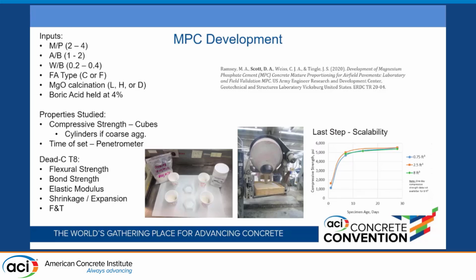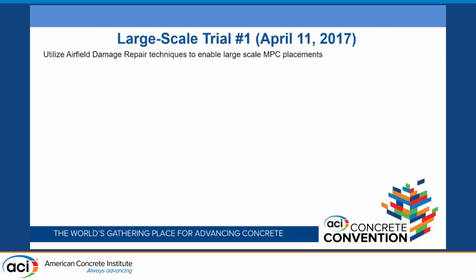So we went through and, all right, we can make it at 1 cubic foot, and it does well. Well, we're eventually going to scale this up large, so we did a scalability study. We made it at 1 cubic foot. We made it at 4 cubic foot, and then here we actually made a half cubic yard, because a lot of times with concretes in general, you can really see your admixture dosages will need to change as you scale your batch. So we were curious about that, and we actually did not notice any scaling issues for our material. So large-scale trial number 1, this was in April of 2017.